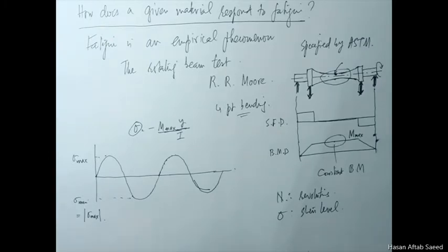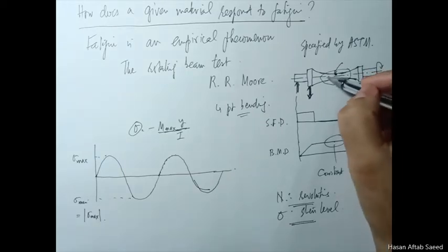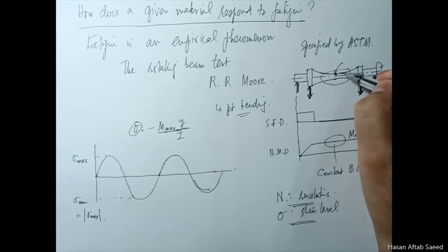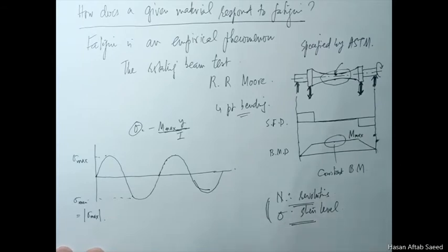Obviously, it's very obvious that for higher stress levels, you'll have fewer revolutions, and for low stress levels, you'll have a high number of revolutions, because if you subject this to a very low stress, then obviously the critical crack length will be very high. So the fluctuations will keep on increasing the crack length, but it will take a longer time, and vice versa. So these should be inversely proportional. We don't know the exact nature of their proportionality, but if this is high, then this must be low. If this is low, then this must be high. We don't know the details, so we'll take that later on.